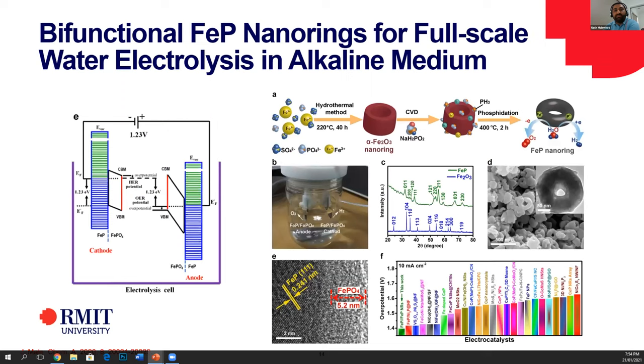Then recently we developed a catalyst that has bifunctionality. We again used iron phosphide, because we know this is an active material, but in our previous study we were not able to fully expose its active sites to the surface. We were not able to create some extra active sites. So here we found that if we can create some strain in the material, that will be very helpful. And then we did some surface modification that also helped protect the material from deterioration.